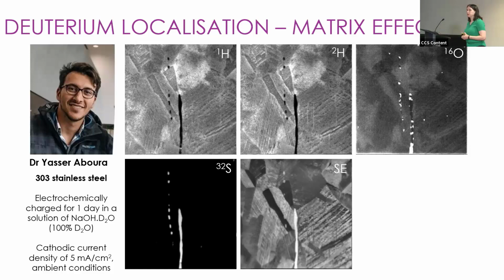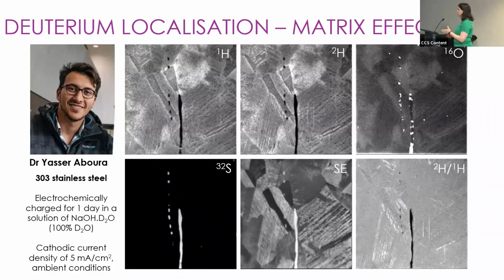Actually, this is just an artifact of the NanoSIMS. What we're getting here is that this particular grain orientation is able to emit more secondary ions than an adjacent grain, for example. So what we do is we actually take a ratio of hydrogen and deuterium, and we generate another image.